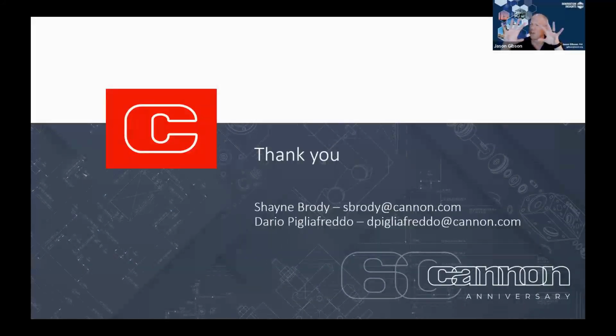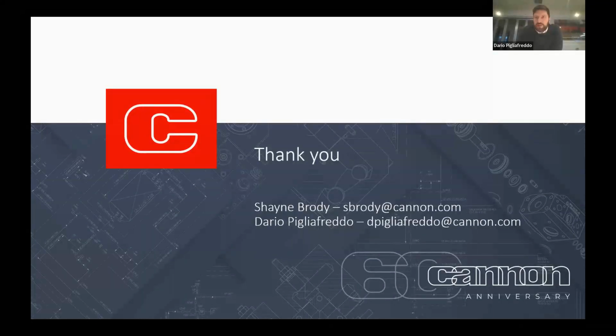And let me back up on your presentation. You had, I think you call it the three-frame system, where you hold the thermoplastic in between the thermoplastic films. I'm assuming those thermoplastic films that are holding it together are part of the finished part after you've compressed. Is that true? Yes, they remain with the finished part, and they protect it if we need, for example, to transfer it. We have customers, for example, who are selling preforms, and this is a good way to maintain it in a certain way. But it's very easy to manually demold it, or we also have solutions that automatically do that, and we are able to transfer it even without the film outside. So depending on the kind of film, it can remain with the part or be taken out.